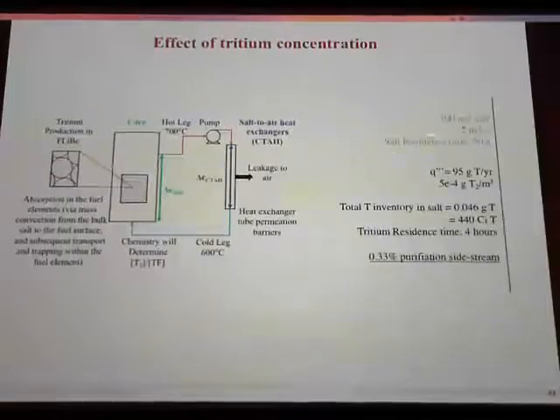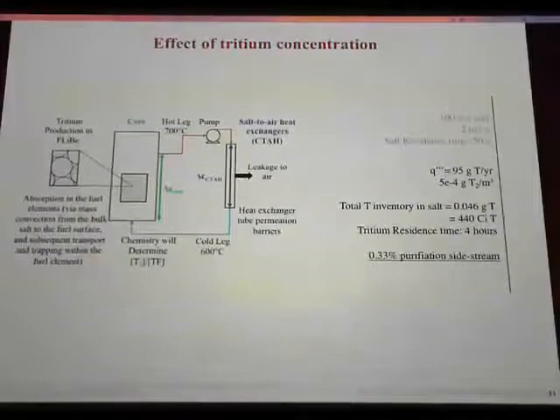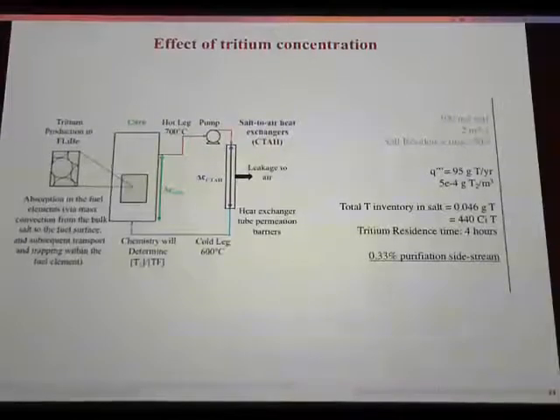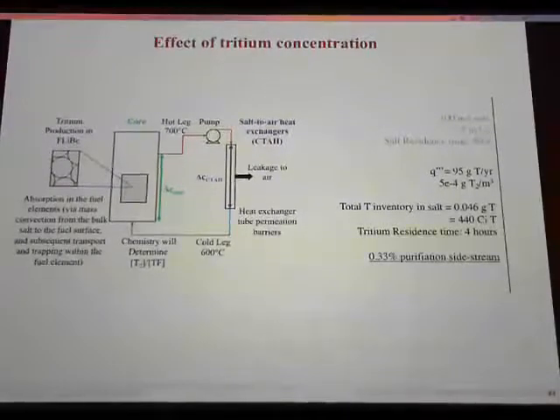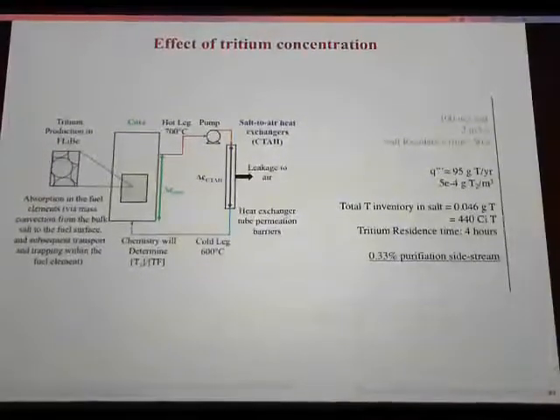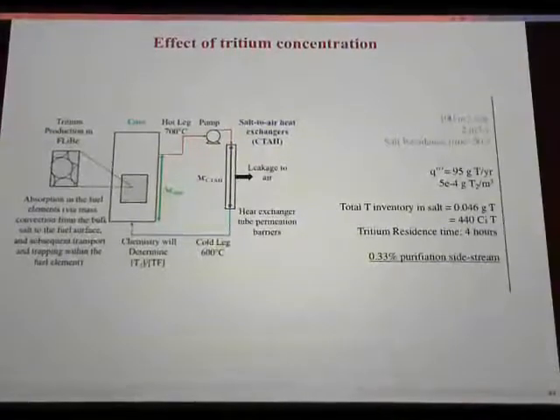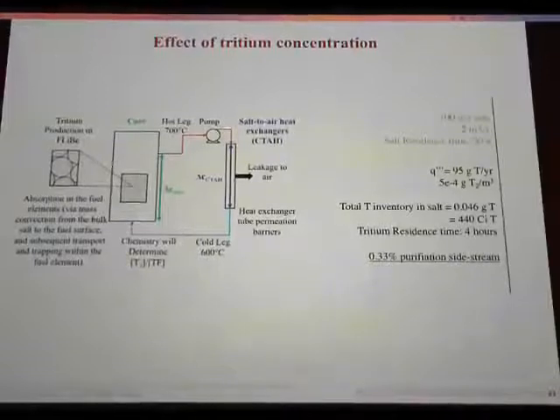We can run the same number on the coolant going around the core. If it runs at 2 meter cube per second, and the total salt inventory is 100 meter cube, then the salt residence time is about a minute. That's actually remarkable, that it takes a minute in full power operation for the coolant to go all the way around the system. This means that in decay heat levels, you're at a half an hour of the coolant traveling around until it makes it back to the core. That's a really slowly evolving system.